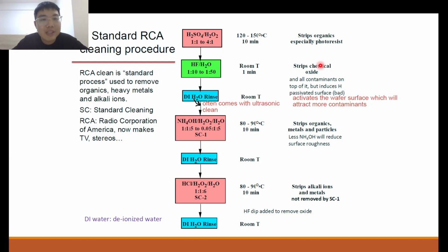Then after that, you may want to use hydrogen fluoride to strip the chemical oxide. However, the main problem with this is that it introduces a hydrogen passivated surface. That means your silicon surface is terminated with SiH bonds, and that's not good because SiH bonds make it easier for certain particles to adhere to and be attracted to the surface, compared to maybe your standard silicon surface with a thin native oxide or something like that. And so this step nowadays is sometimes skipped because of that reason.